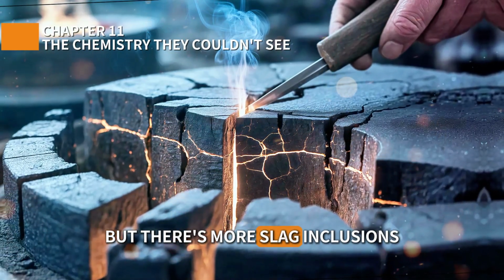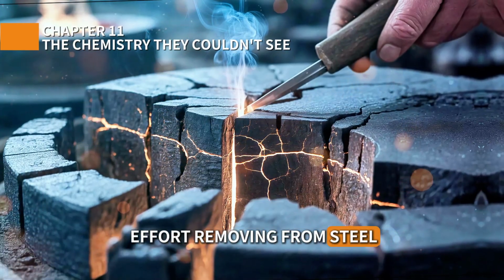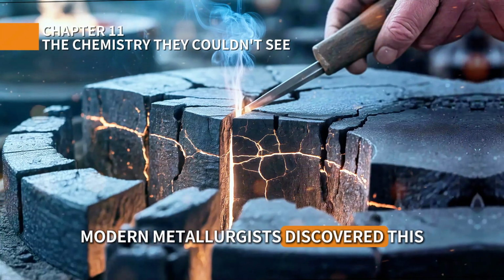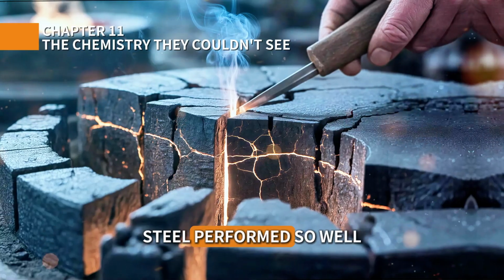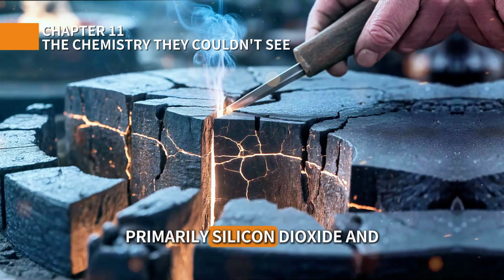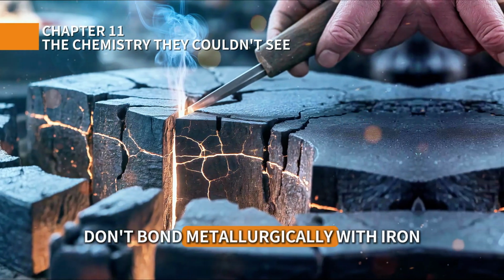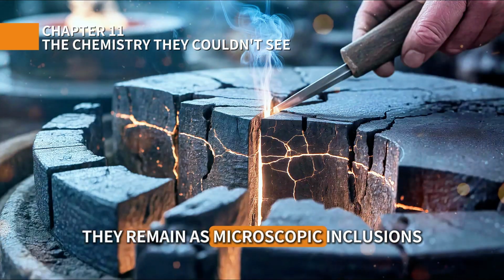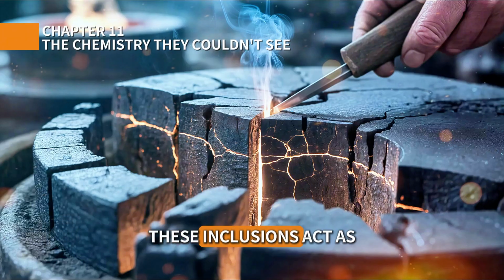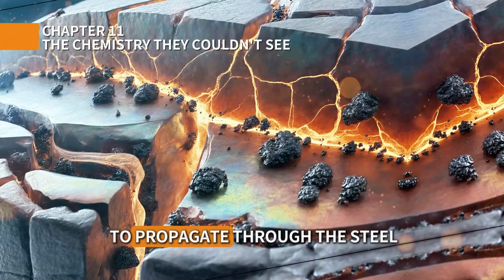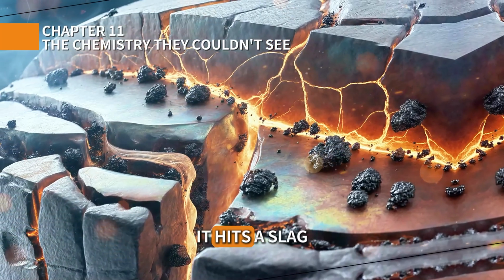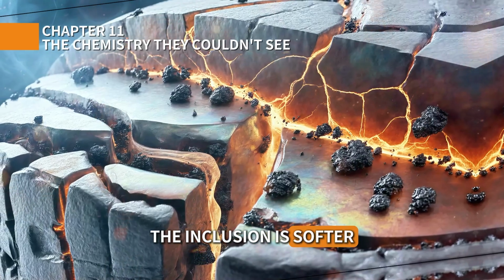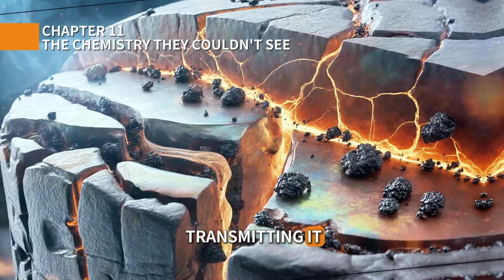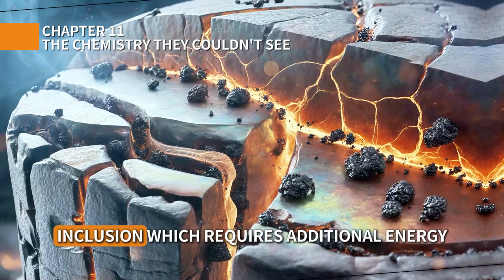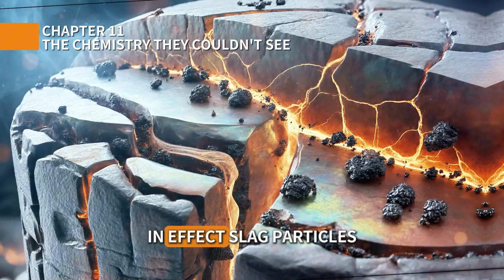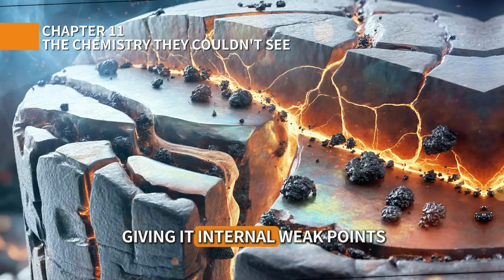But there's more. Slag inclusions, impurities we now spend enormous effort removing from steel, actually improved medieval blades. Modern metallurgists discovered this by accident, while studying why ancient sword steel performed so well. Slag particles, primarily silicon dioxide and calcium compounds, don't bond metallurgically with iron. They remain as microscopic inclusions throughout the steel matrix. These inclusions act as crack arresters. When a crack begins to propagate through the steel, perhaps from impact or thermal stress, it hits a slag inclusion and stops. The inclusion is softer than steel, absorbing energy rather than transmitting it. The crack must reinitiate on the other side of the inclusion, which requires additional energy. In effect, slag particles make steel tougher by giving it internal weak points.